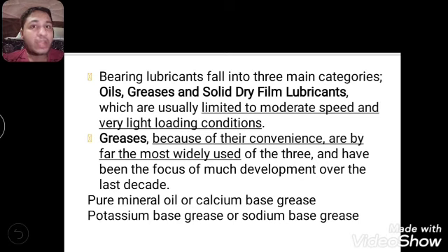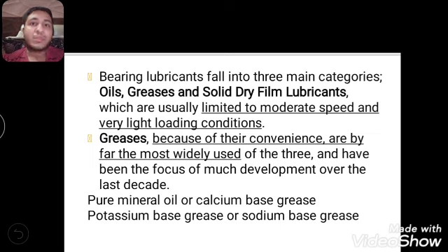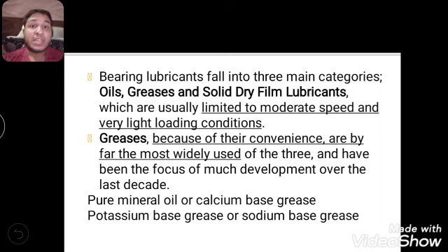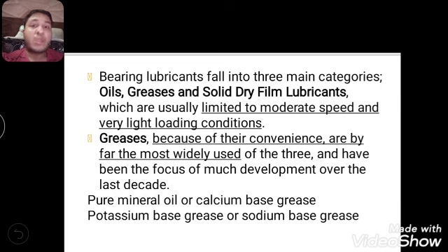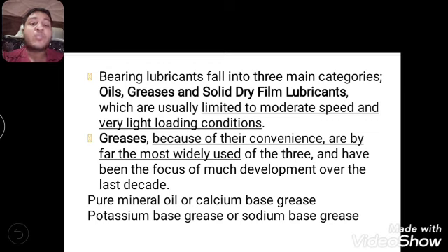The two main types are pure mineral oil in the oil category, and calcium-based grease. Remember that calcium-based grease is preferred when used for general bearing lubrication. Potassium-based grease and sodium-based grease are preferred when the bearing is going to operate in an area where it will face moisture content — in conditions where moisture is present, potassium-based grease and sodium-based grease are used as the lubricant.